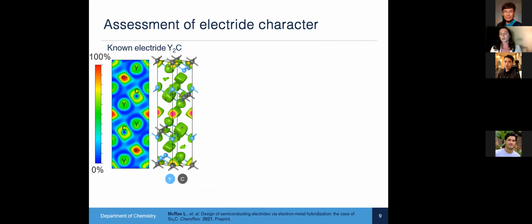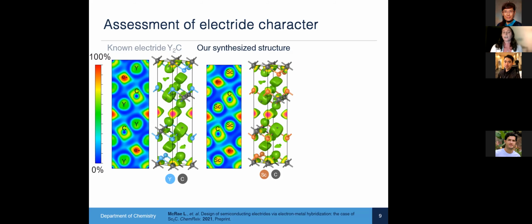And so if we were to see that in the discandium carbide, we would say that that is also an electride. And that is in fact what we see. So we again see the same structure with the same electron sites. And so it looks like this layered structure that we were able to predict is an electride. Now, this is the most electronegative cation that's been incorporated into an electride. But our question then became, how electronegative can we go and still see electride character?